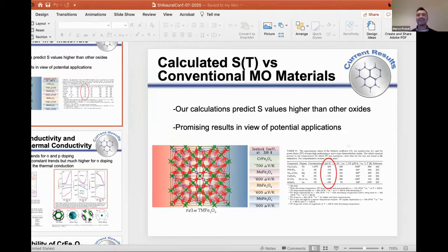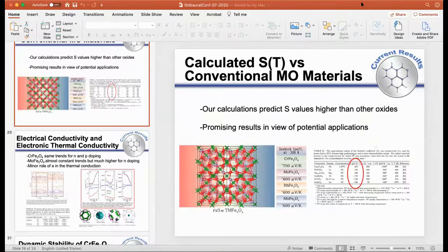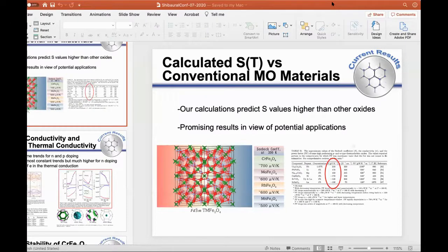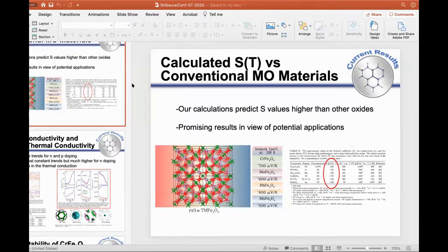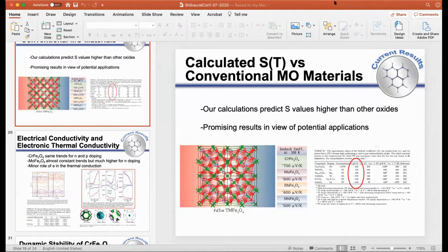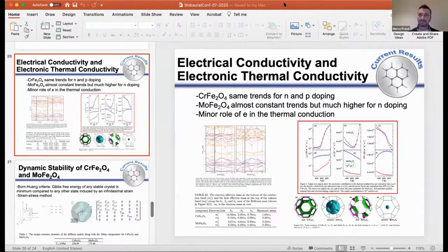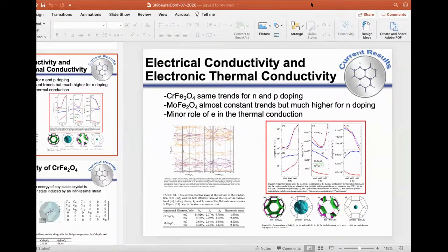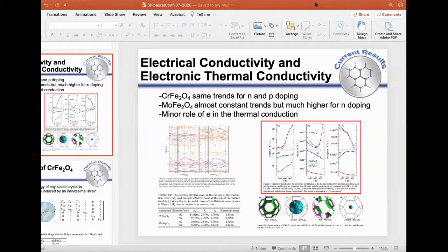Okay, I can change my comment. My opinion is that the weak point of the oxide is not actually the low Seebeck. It's the low carrier mobility. If you wish to gain high electrical conductivity, you will dope the carriers, and then the decrease in Seebeck is rather steep compared to other materials.